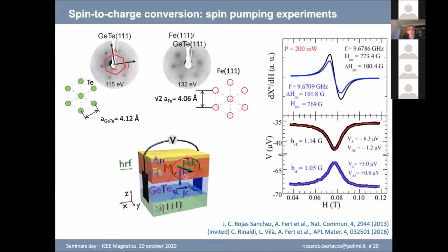Then you excite now a precession, and when you are at the ferromagnetic resonance, there is a channel for momentum relaxation which corresponds to this injection of the spin current here, JS, in the germanium telluride film. And what happens is that if there is any spin to charge conversion, there will be now a current JC flowing in this direction that gives rise to a voltage drop which can be measured. So by measuring this voltage drop, you really observe, and we observed and we published that a few years ago, that there is a peak now in the spin to charge conversion, the charge current JC, in correspondence to the ferromagnetic resonance. But at that time it was really impossible to control the ferroelectric states.